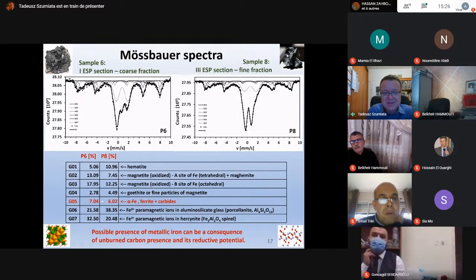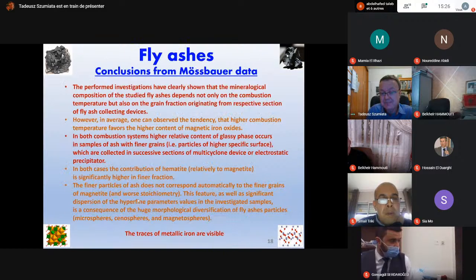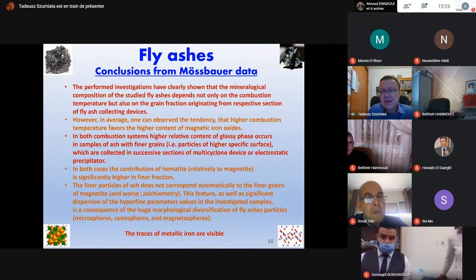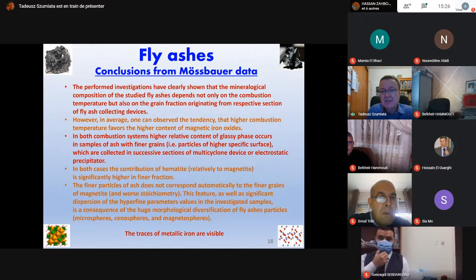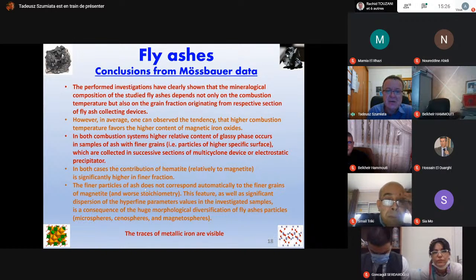And we also can see more metallic iron here. So two different systems, two different situations, but the same thing, that during the burning of the coal, we can expect some traces of metallic iron. And it is, I think, the main conclusion from this part, but we can also see some other details. For example, the detailed mineralogy of these ashes depends not only on the burning temperature, but also on the granulometric fraction. But there is some general tendency that the higher the combustion temperature, the higher the content of magnetic iron we can expect.